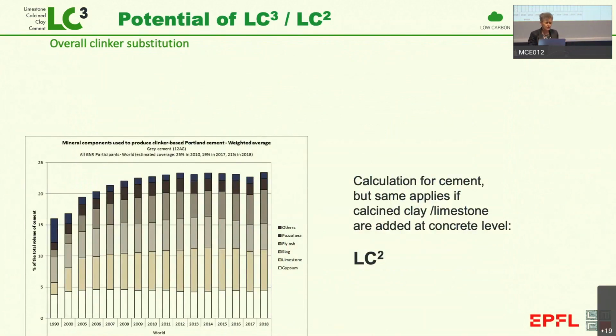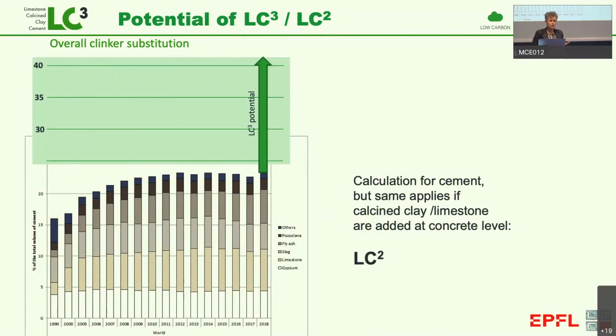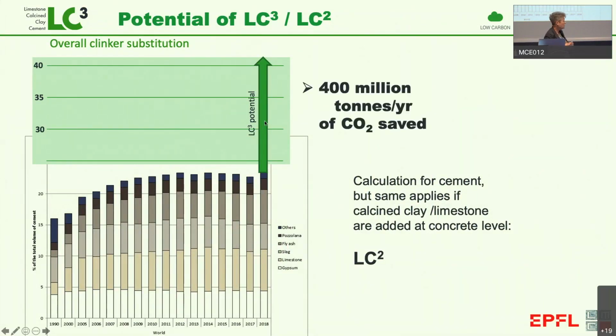So if we go back to this picture, which is the level of substitute materials in the world, you see this is stagnated just below about 25%. Now, on a basis of technical performance, we know we could go to a level of substitution on average of about 40%. So if we calculate this extra we could get, this amounts to 400 million tons of CO2 per year. So that's, just to put in context, 10 times the entire emissions of Switzerland we could save on a worldwide level.